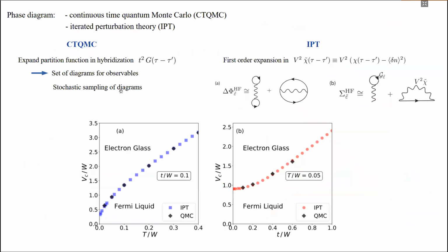In order to obtain this phase diagram, as I already mentioned, we applied two different methods, a continuous time Monte-Carlo method and an iterated perturbation theory. I won't go into the details now. I would like to mention that here I show two cuts of the phase diagram calculated with the two methods, and we get results that are very close to each other. So we can use the continuous time Monte-Carlo method to validate our iterated perturbation theory.